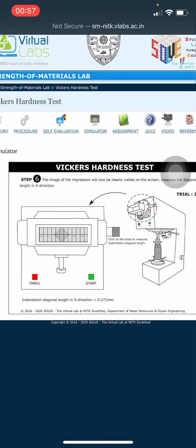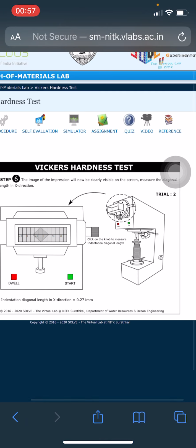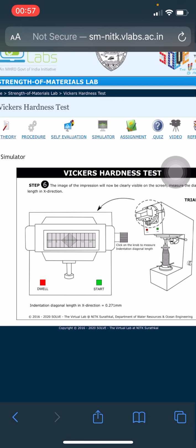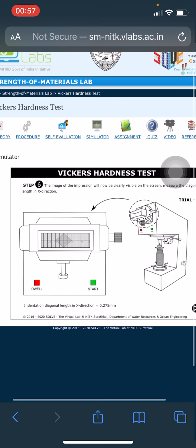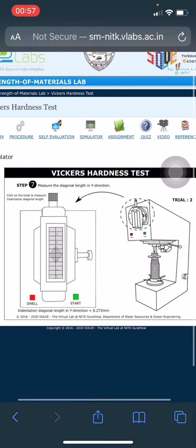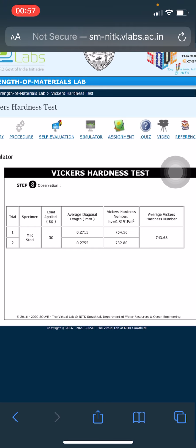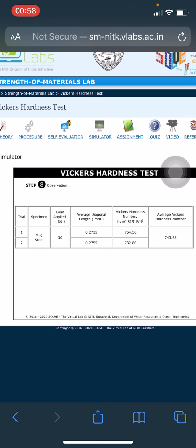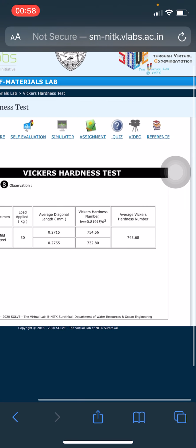Click on the knob. Step 6. The image of the impression will now be clearly visible on the camera, on the screen. Measure the diagonal length in the X direction. Step 7. Measure the diagonal length in the Y direction. Click on the knob to measure the indentation diagonal length. So the observation: trial 1 and 2, mild steel, load applied 30 kg, average diagonal length, Vickers hardness number, average Vickers hardness number. We have 2 trials in this experiment. So we're done with the simulator.